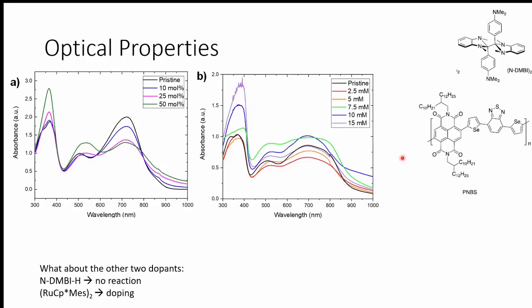Now, let's start by looking at how these different dopants are going to react with my polymer. When I dope this PNBS with the N-DMBI dimer, you start seeing changes in the solution spectra. Again, these are hard to pinpoint exactly, because there is a lot of charge transfer absorption between the different donor and acceptor units on the polymer. But what we rely on is whether there is a trend of something constantly increasing versus decreasing. And we see that in the solution state, so we know there is a reaction happening.